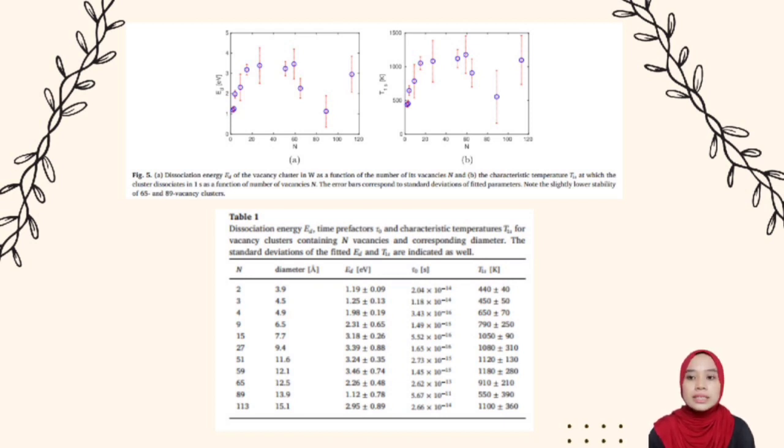From the calculations, these nanovoids are stable at room temperature. If one extrapolates the obtained values to an annealing time of 1 hour, then these nanovoids will lose a vacancy in 1 hour at 700 plus minus 200 degrees Celsius.